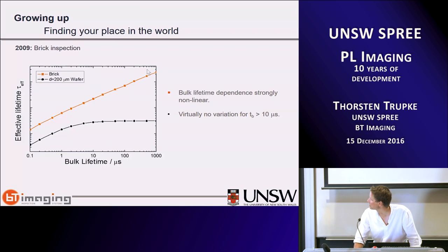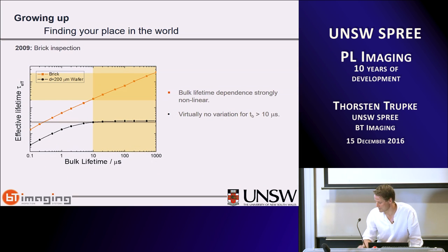The situation is different for a brick. That's shown here, basically. On the d=200 µm wafer, this entire lifetime range is squeezed into this narrow gray bar, whereas on a brick, we still have a factor of 10 in measured lifetime, which enables us to correlate the measured lifetime with the bulk lifetime.